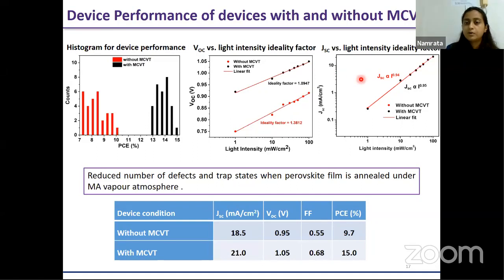And further, when we looked at the JSC versus light intensity ideality factor, again we have a value nearer to 1 for the perovskite annealed under the methyl ammonium chloride vapor treatment. So this clearly shows that the vapor atmosphere treatment reduced the number of defects, and all the device parameters were enhanced. We can see from the table below that we had a good improvement in the JSC. Of course, open circuit voltage is very important, where we have a 100 millivolt improvement, and the fill factor is drastically improved, which leads to a power conversion efficiency of 15%, whereas without the annealing treatment we just had 9.7%.